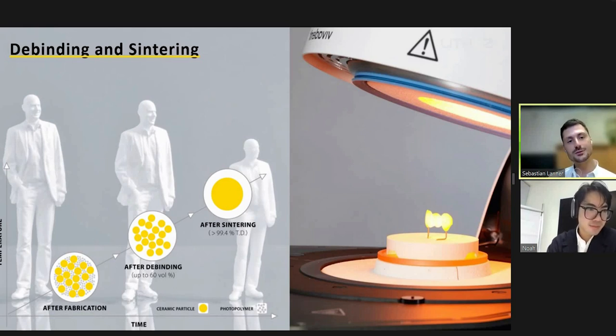And here, this is a little bit different to milling, as we have two steps in here. One is debinding and one sintering. I'd like to explain it on the left picture. This is a part basically printed from our CEO, Dr. Johannes Homer. On the left side, you see the part directly after printing and cleaning, and you also see an image of the particles. We have the yellow ceramic particles, and as well some polymer particles. These polymer particles helped us to shape the part, and now in the debinding process, we want to get rid of them. Basically, we burn them out. So we use heat to burn out all the polymer, and then we get to the part in the middle where you see only the ceramic particles without any polymer.